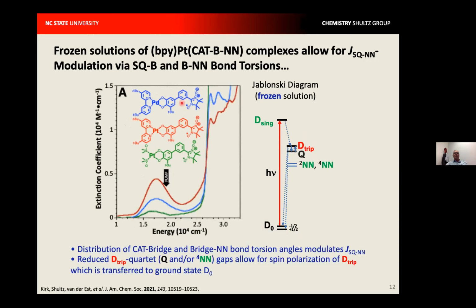And so we made some complexes, and in particular, we made a complex where we got rid of the diimine ligand that gives us the ligand-to-ligand charge transfer transition. And by doing so, we reveal what many of you already know, that nitronyl nitroxide radicals themselves have an excited state that is nearly coincident with the energies of the ligand-ligand charge transfer excited states. And Marty Kirk's calculations suggest that the quartet that belongs to this doublet transition for the nitronyl nitroxide is also very close in energy to that spectroscopically observable doublet.